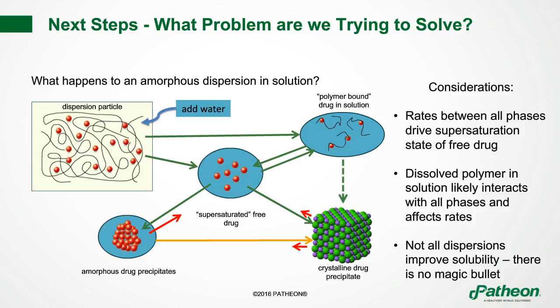But what happens is you've got these competing forces, and the green arrows and the red arrows are basically the rates of change between those different species. So in the lower left, you start to see amorphous drug precipitates, and this always happens. The extent to which this happens is what we're trying to minimize. But it does typically always happen. And you also see crystallization of drug. You see drugs start to precipitate out as crystalline too. And you see interconversion between the amorphous and the crystalline. But by modifying, one, the nature of the loading of the drug in the dispersion, and two, the nature of the polymer and how it maintains the drug in solution, you can enhance the supersaturation and inhibit the crystallization and the amorphous precipitates.